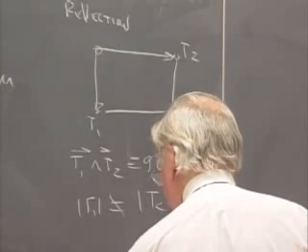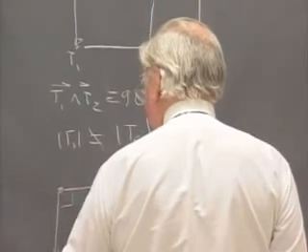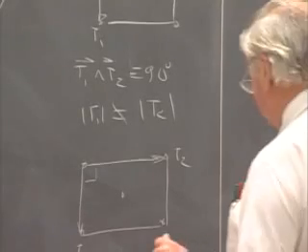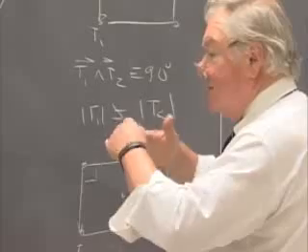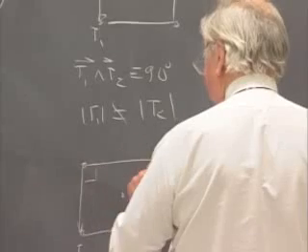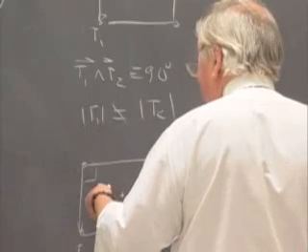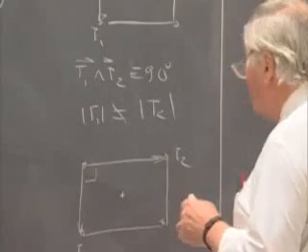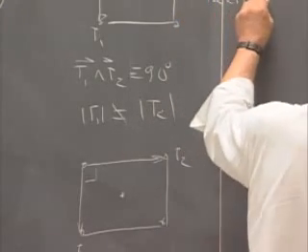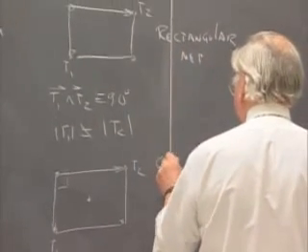but it was operationally much to our advantage to pick a double cell which had a right angle in it. The reason for that was that it is a nightmare to do calculations of interatomic distances and angles, or angles between faces in an oblique system. The right angle makes these calculations very simple. And the fact that this cell tells you twice as much of the area as you really need to know about is a small price to pay. So this is the rectangular net, as we'll call it in words. And this is one that we'll call the centered rectangular net.